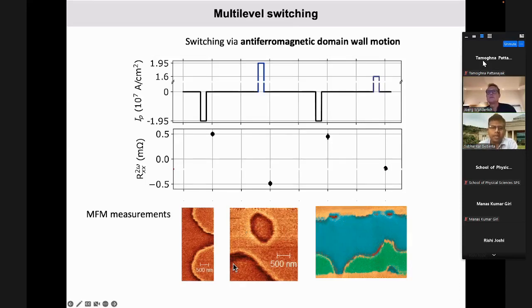Okay, but then I wonder, if you take an image of just one layer, using a technique which is just surface sensitive and sensitive to the top ferromagnet, would you expect a similar structure, or a different structure? Definitely, those antiferromagnetic domain walls here are the boundaries of domains on the upper and the lower layer. Because the RKKY interaction is quite strong.